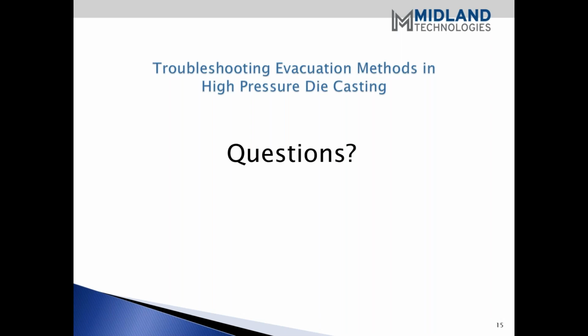If you've used adequate venting, either with the chill block, conventional vents are fine, except for the problem that they really don't have the area necessary to evacuate, because the space that you have usually to atmosphere is only 5 to 6 thousandths, times whatever the actual width of the evacuation path is. So using either some means of a chill block or a vacuum assist is real beneficial in that instance.